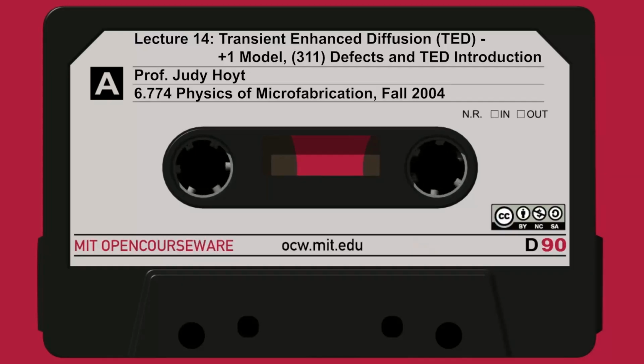So here is an experiment that was done. This is a concentration as a function of depth, so maybe a SIMS profile. And the initial profile before any annealing looked like this. You have very low boron at the surface, and then you have a boron marker layer. At some depth, there's a boron layer that's doped about 1E18. This marker layer can be put in a variety of ways. It could be put in by epitaxial growth, whatever. It's a region that's boron doped. We call it a marker layer. It could be the base of a bipolar transistor for all we know. And it looks like a box initially.